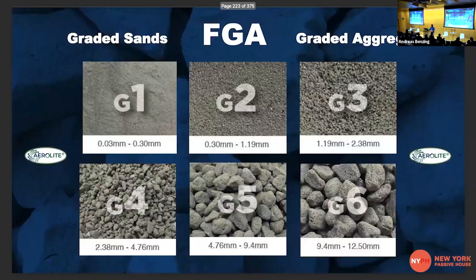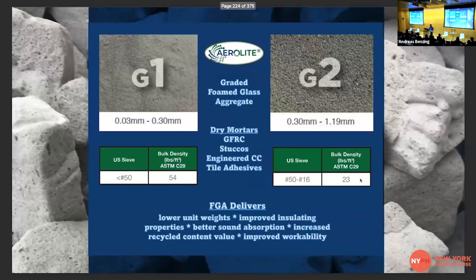Another same project, Hilton Garden Inn. I want to talk quickly about the graded aggregate. So now what we're doing is we're taking the larger pieces and we are sizing these materials down for use in concrete. So again, if you take a yard of concrete and you have 19 cubic feet of mined sand and aggregates, you literally can take that material away and you can replace it with a graded aggregate. So this material is 100% recycled content, displacing natural aggregates.